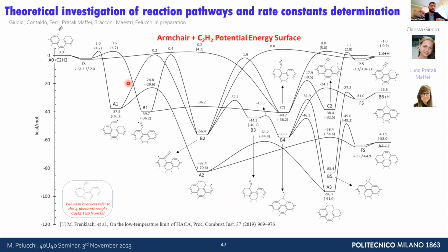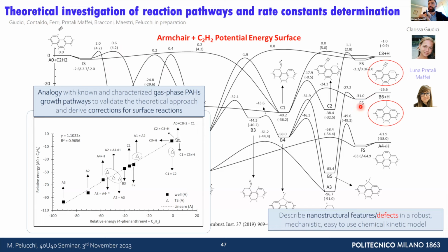In reality, if you look at the potential energy surface constructed in this work by Clarissa, which we're about to submit, done using a PBE-D3 functional with periodic plane wave boundary conditions, we're focusing on a 50 carbon atom cell, not an entire graphene layer. You see that many pathways give access to something that is not exactly graphene-like carbon, but has moieties with different reactivity, or even a five-member ring. A five-member ring, as everybody knows from PAH chemistry, starts a curvature when it forms, and that has an impact on mechanical and other properties.